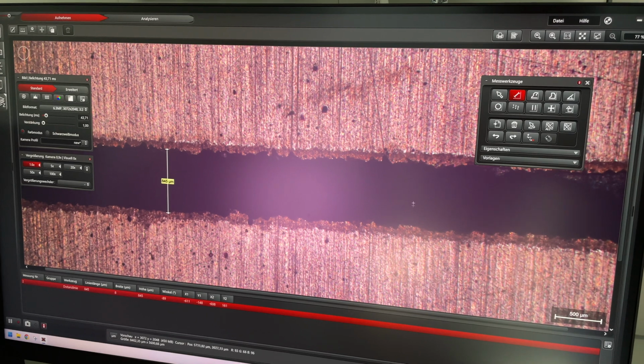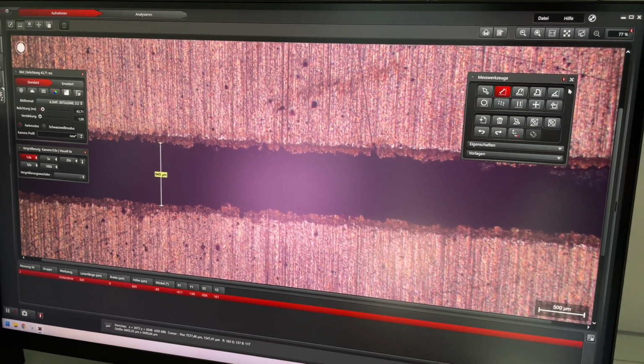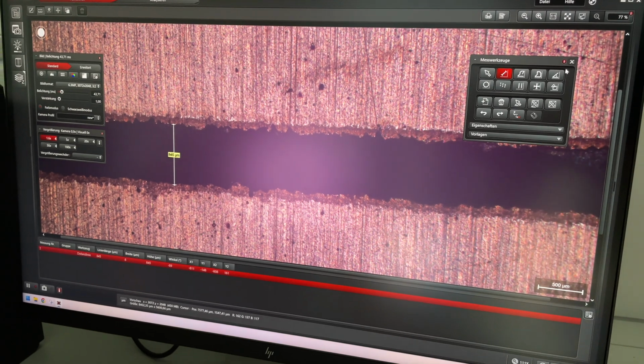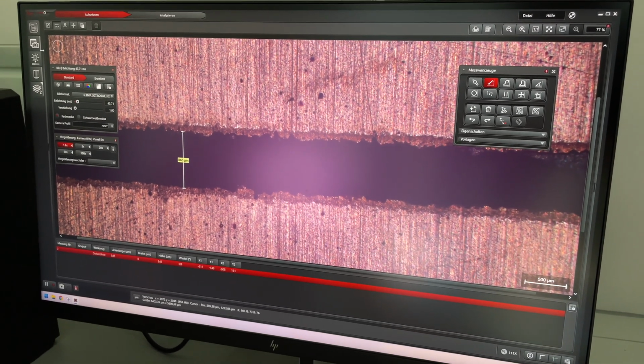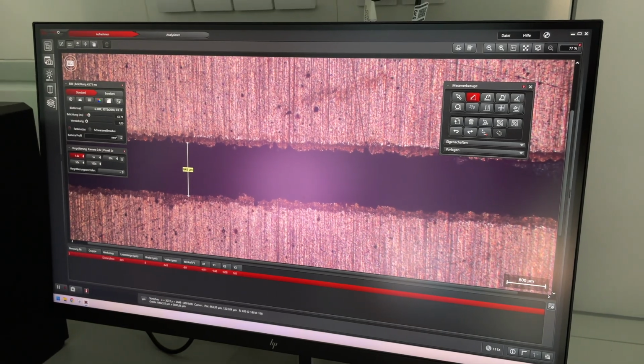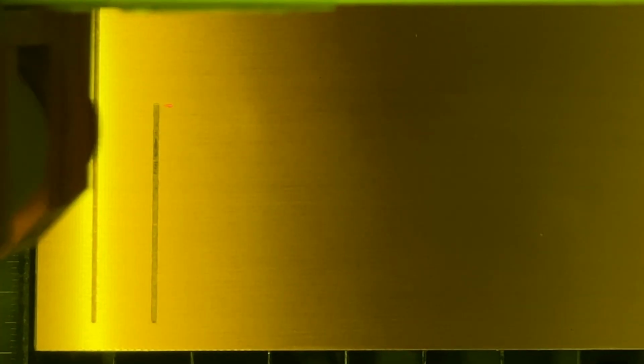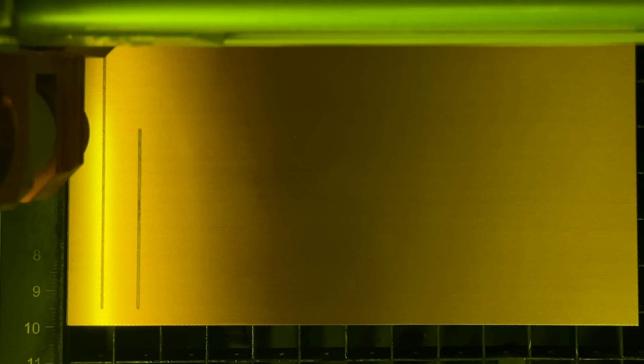If we take a look on the screen at the results, we can see that the copper is completely gone in the etched areas, and the edge itself is actually quite good. It's a little bit rough, but better than expected, especially if you take into consideration that the laser was running from the left to the right. So it's always accelerating, braking again, accelerating, braking again. Repeating this process with high precision is not an easy task, and having such a good result on the edges is actually quite good. So we've been quite satisfied, and we will go for a full layout, using the laser to burn away the coating completely, and then go for etching with the optimal settings we just found in our experiment here.